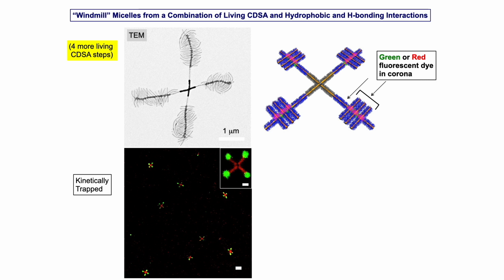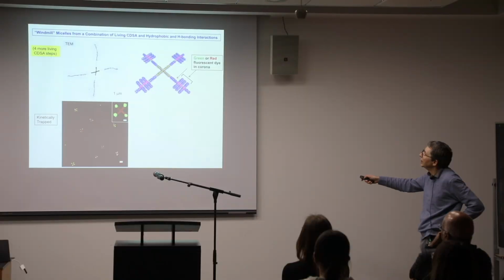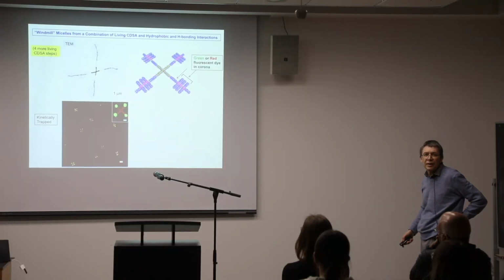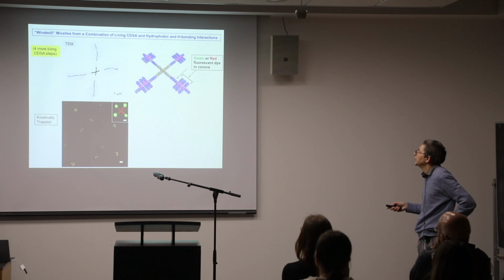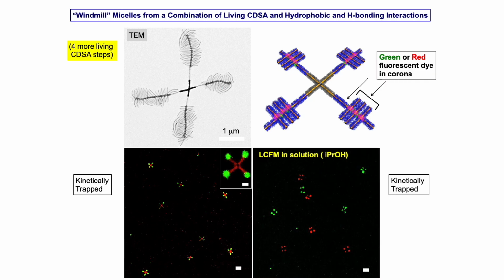We put green fluorescent dyes in the end and red fluorescent dyes along here, so you can visualize them in solution. These are very stable structures. We've made samples where all the dye is green and samples where all the dye is red, and when you mix them, we wondered whether there would be any exchange, but actually very, very stable. So the green windmill micelles remain as green windmill micelles, and the red ones remain as red ones.